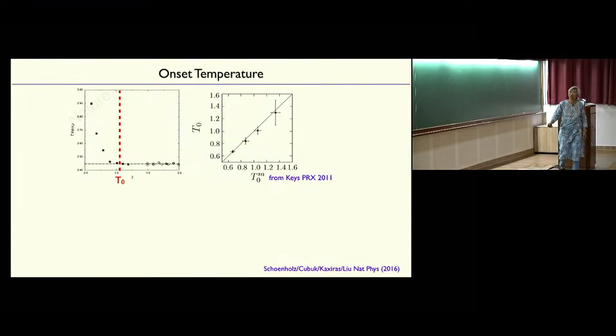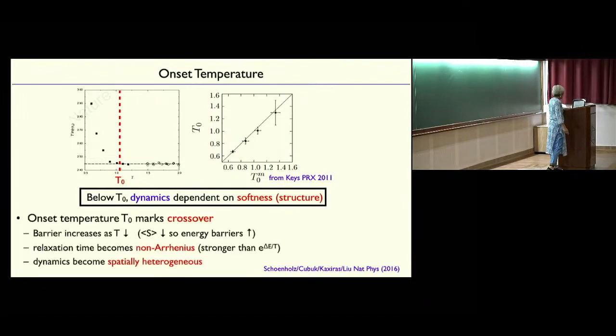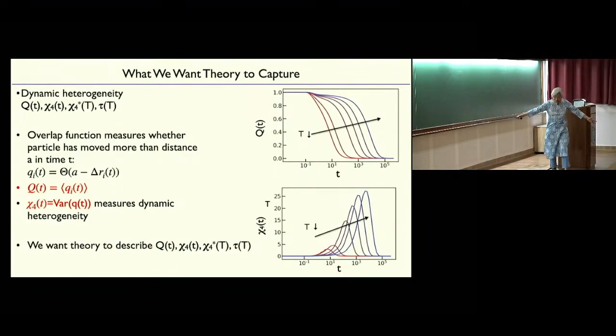So here's the onset temperature that you measure from the kinetic heterogeneities. This is a paper by Aaron Keys, Sharon Glotzer, David Chandler. They measured the onset temperature in a totally different way. We compare it to our onset temperature. The dotted line is equality of the two. And that is the temperature where the energy barriers start getting bigger as you lower the temperature, and the temperature at which the dynamics become spatially heterogeneous. So now we're ready to tackle kinetic heterogeneities. We've got the tool in hand. So how are we going to calculate this?